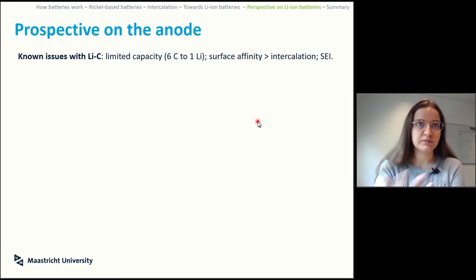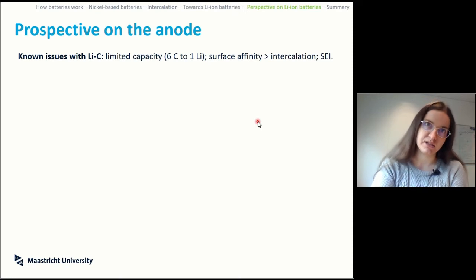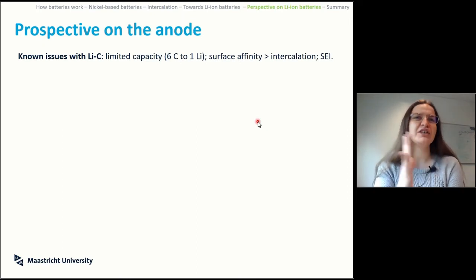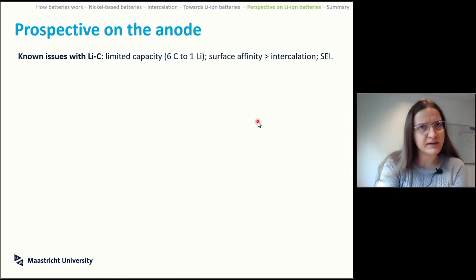So the anode, we know it's lithium intercalated in graphite. We know that the capacity here is limited, whereas if you were to have lithium metal, you will have 100% lithium constantly available. This is LiC6, so there is one lithium for every 6 carbon atoms in your intercalated structure. And it tends to have a bit of an issue putting stuff back inside. It is much more common that there will be a surface affinity, so stuff stays on the surface, than going inside and actually intercalating. This is an issue of the energetics of the whole process.